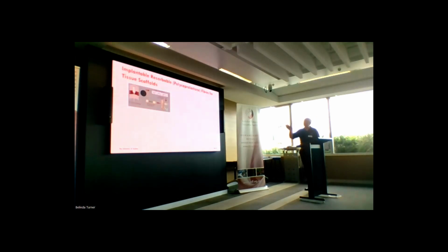We've also been drawing polycaprolactone. It's a resorbable polymer, and we have been using this with a view to tissue scaffolds. So plasma treating, so we can surface functionalize, stick growth factor on, put in stem cells, and use that for guiding the cell differentiation as a way of building up a structure which would then be implanted for someone who's lost key tissues through trauma or disease.